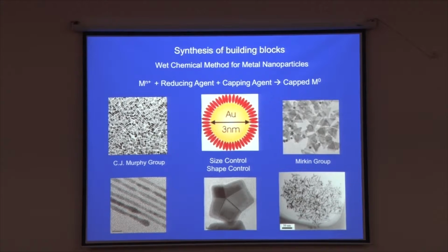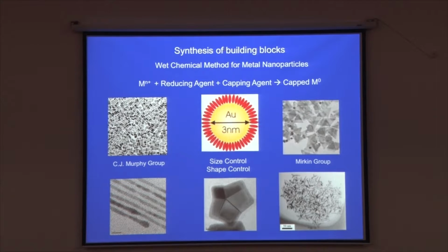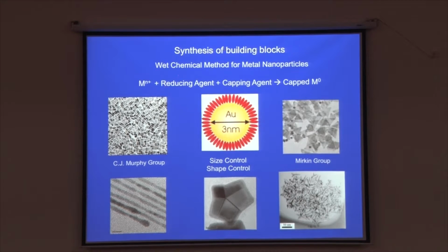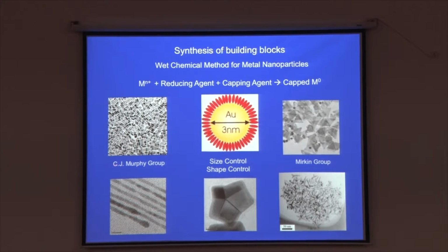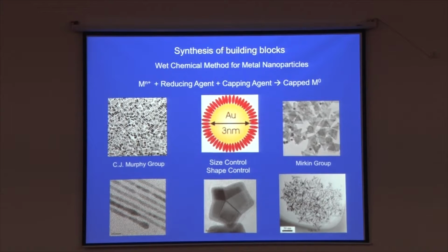We have another ingredient here which is called a capping agent. The primary purpose of the capping agent is to go and attach itself or adsorb on the surface of the growing crystal. That is what basically defines the size and shape of the crystal that you are going to have. The capping agent is an adsorption-desorption equilibrium. It is not a static situation. Therefore, with a small change in reaction conditions and the ratios of these reagents, you can get a very large variety of sizes and shapes. So this is what wet chemical synthesis of a simple metal primarily looks like.